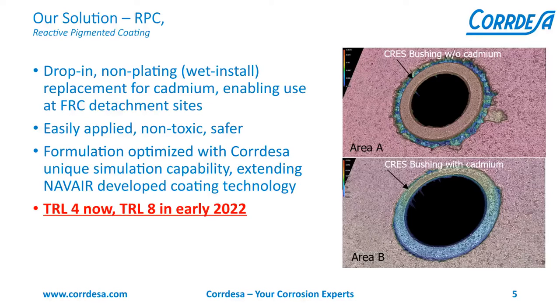Our solution is reactive pigmented coatings, or RPC. If you take a look at the photographs on the right, you can see a bushing inserted into an aluminum structure. Despite the use of corrosion-resistant steels in the top image, area A, you see the impact of the galvanic corrosion between the untreated steel bushing and the surrounding aluminum structure. Whereas in area B below, when the bushing is treated with cadmium and wet installed with a standard hexavalent chromate primer, galvanic corrosion is avoided.